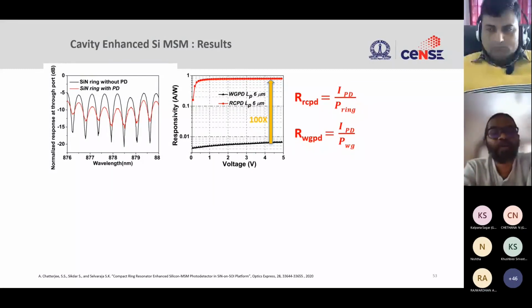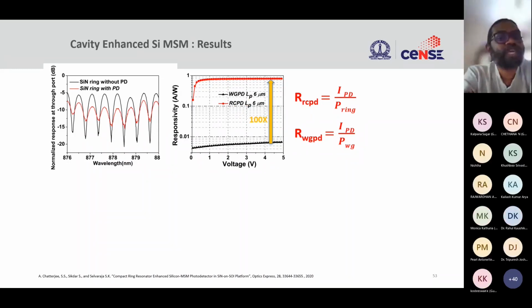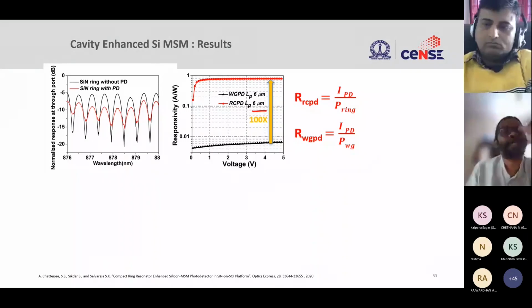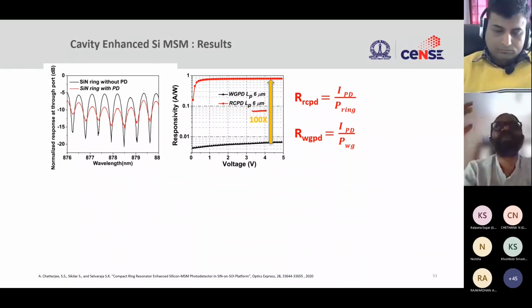We looked at what we call a ring cavity photodetector, that is RCPD, and this is a waveguide photodetector. We saw about 100x improvement in the responsivity. If you remember, we talked about a maximum responsivity of 0.4, and that was for about a 100 micron long detector. But here we are talking about a very small, 6 micron device. And by the way, for some of you who are trying to understand what this 6 micron is, the diameter of a human hair is about 120 micron. It's reasonably large. I'm talking about 6 micron, much smaller than that.